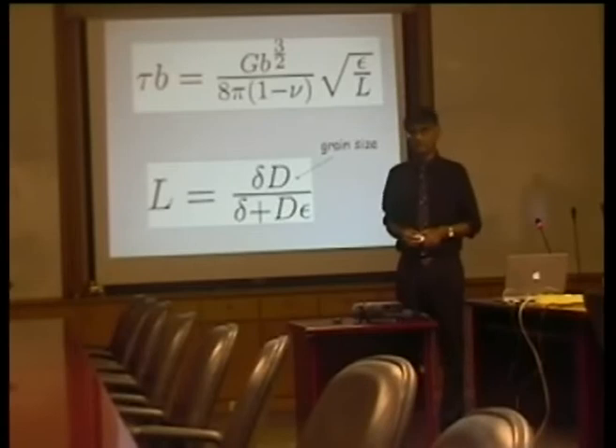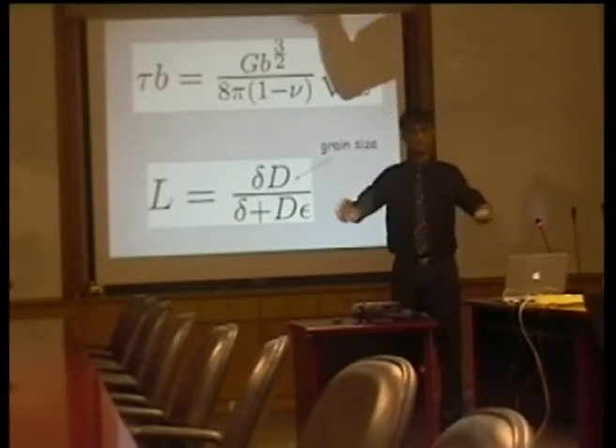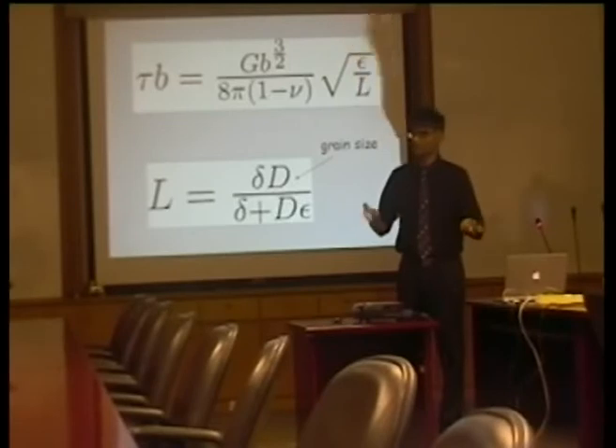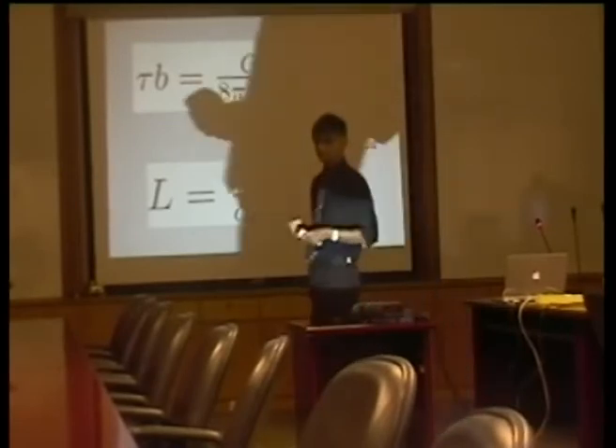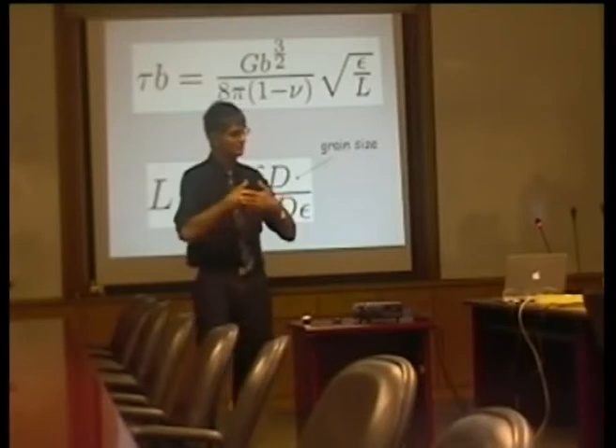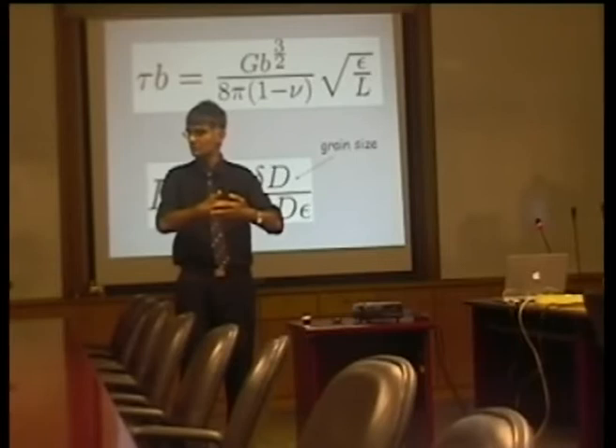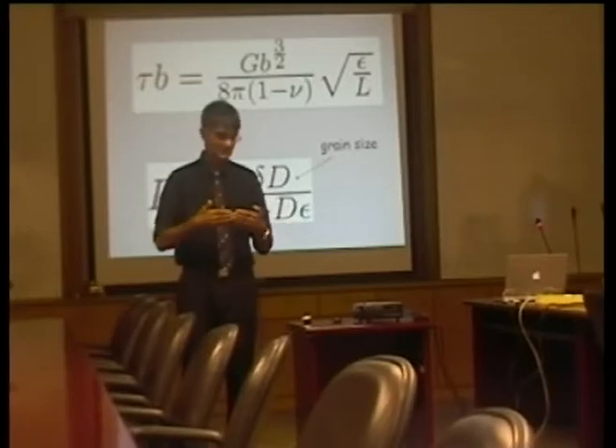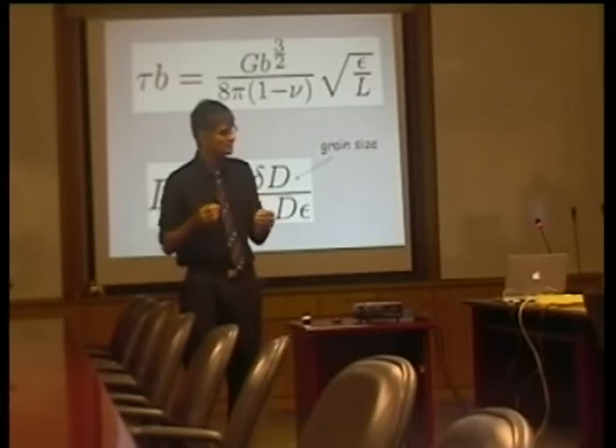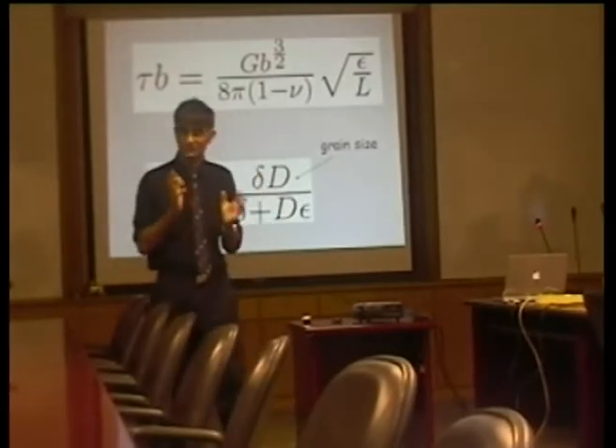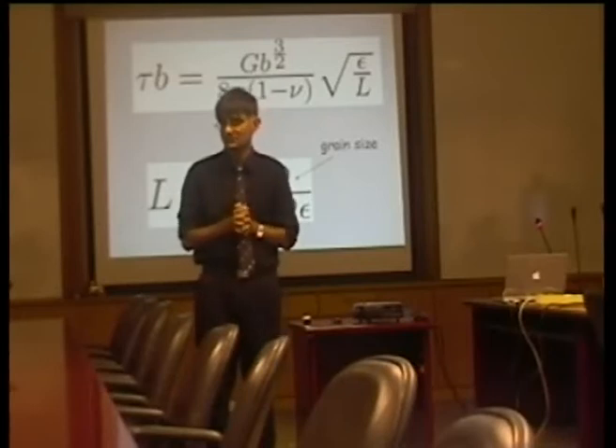Now why am I working out the stress required to move dislocations in this jungle of dislocations and boundaries? The reason is that we've got a martensite-austenite interface and it has to push against these dislocations. If it cannot overcome those dislocations, martensite cannot form. So the theory is that if the driving force which pushes the martensite-austenite interface is not large enough, then you will stop martensitic transformation. So this is the first ever theory for mechanical stabilization.